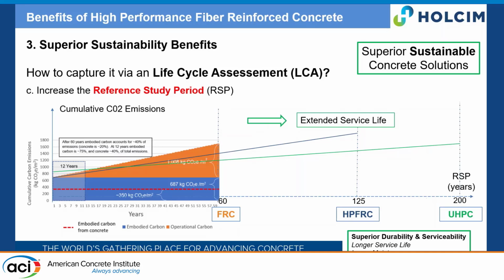You can imagine that typically for buildings, the LCA is run for 60 years. If after 60 years you need to tear down the building and rebuild it again, you come on top and add it. From the get-go, if you design with high-performance fiber reinforced concrete or UHPC, you may have a higher upfront embodied carbon, but in the long run, over 200 years, or 150 years, for example, the longer service life will give a better footprint.